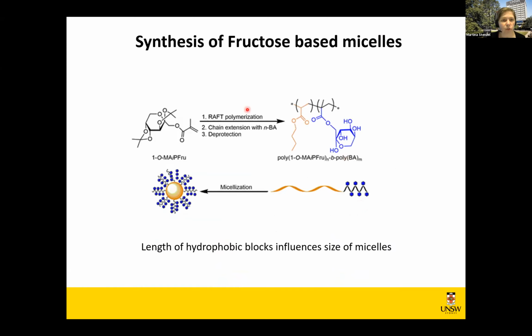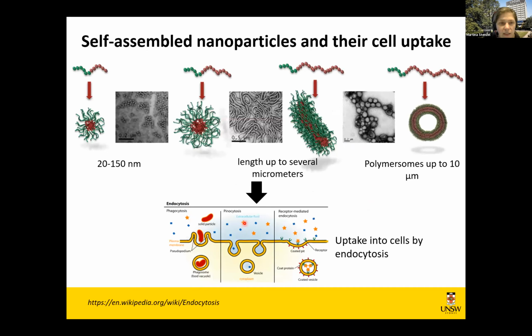glycopolymers using a process called RAFT polymerization. It's a very easy way to get a whole range of so-called block copolymers. In these block copolymers, we can easily change how long we would like that hydrophobic block to be and how long we would like that glycopolymer block to be. The length of the hydrophobic block very much influences how big our micelle is going to be. So this is a very nice tool to get nanoparticles of different size and different shape.